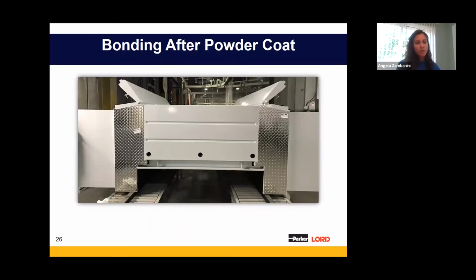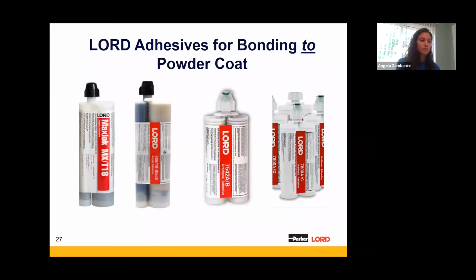Okay. Now this is an example of another customer that I work with who is bonding after powder coat. So now these are the adhesives we recommend if you prefer to bond after the powder coat, which for some processes works better that way. So you can use the Maxlok and the 400 series for both before and after powder coat and E-coat, which really makes it great to have as a product in your shop because it can do both. It could also cross bond as well. So if you wanted to bond bare metal to painted metal, you could use the Maxlok with the 400 series